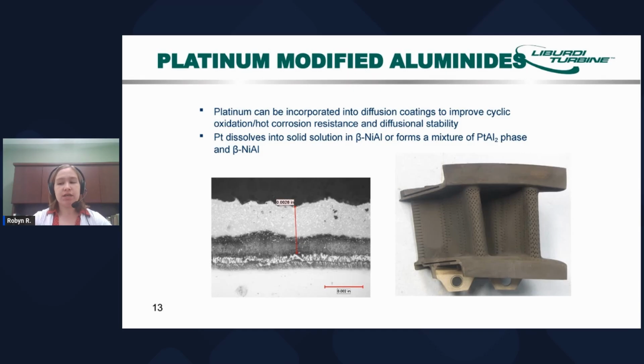A common addition to the aluminide coating is platinum. It's often incorporated into aluminide diffusion coatings to improve cyclic oxidation resistance and is often used in components that see a lot of potential hot corrosion damage, such as that LM2500 Row 2 vane as shown before. The platinum dissolves into either a solid solution in the beta aluminide or forms a mixture of platinum aluminide phase with the beta aluminide. So the micro on the left shows the LSR platinum aluminide coating with the light region showing the platinum rich layer of coating.